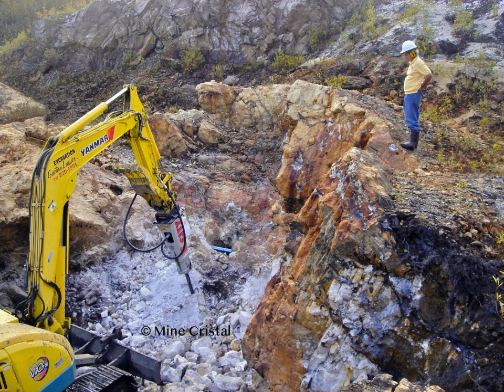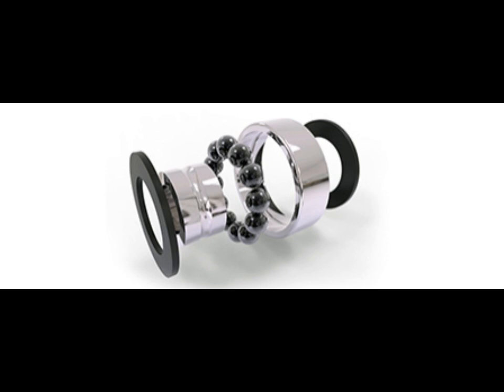Also, depending on what you are going to make, some additive might be included to help in the sintering process. If we were going to make a ceramic bearing ball out of silicon nitride, we would start with pressing the powder into a preformed spherical shape. Take that part to be then sintered with hot isostatic pressing. After that, the ball is inspected for imperfections and put through a grinding process with diamond grinding tools because of the high hardness of the product. Some manufacturers also use chemical mechanical polishing to get that mirror-like finish to the object. This process can take months depending on how precise and good quality the manufacturer wants to make their product.